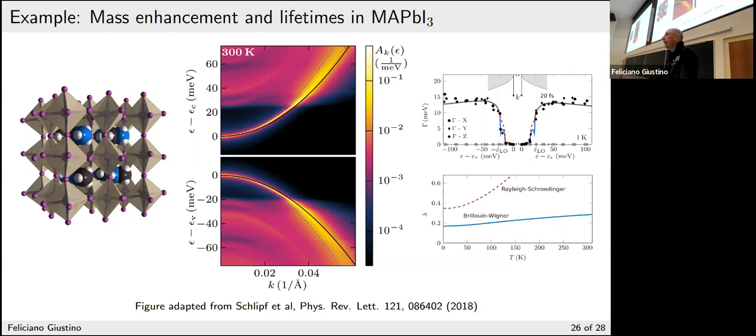Now you can calculate how much the effective mass has increased, and that is on the order of between 0.2 and 0.4, so between 20 and 40%. So the electron is a little bit heavier than without electron-phonon interactions. Here, for this lambda, there are two lines that I'm showing you, and these correspond to two different ways of evaluating this mass enhancement. This is just a warning that in the world of many-body physics there are many loose ends, because there are several ways of doing calculations. It's not a variational approach like in DFT, so depending on the choice you make, you may get different values, for example 0.2 or 0.4. One has to be very clever in making choices that are directly comparable to experiments.